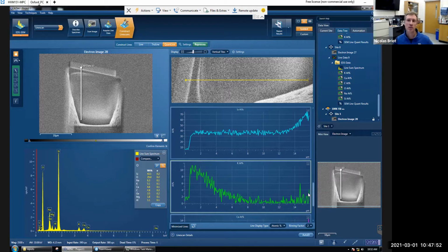That cross-section polisher I mentioned is made for cross-sectioning, of course, but it's also called a polisher because you can also put samples that have been prepared manually flat and do grazing incidence while the puck rotates. So you have a really nice polish that doesn't involve any mechanical grinding. That could also erase those regions that have been mechanically damaged. I think we'll play with the machine and see the different approaches.